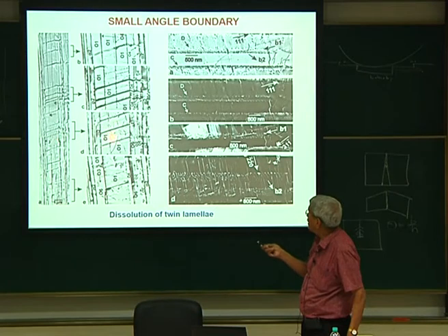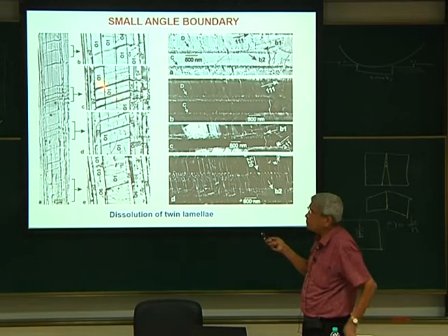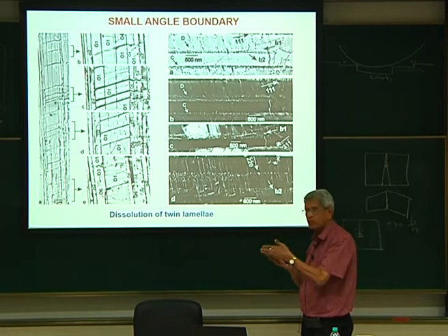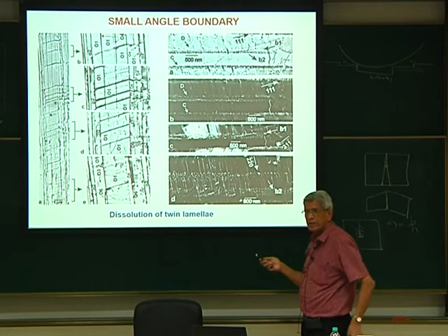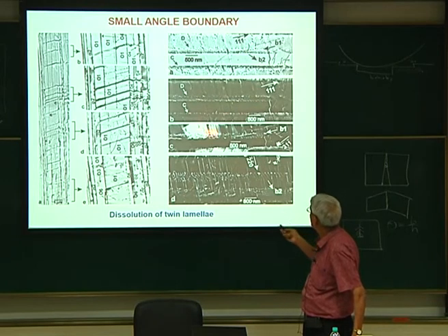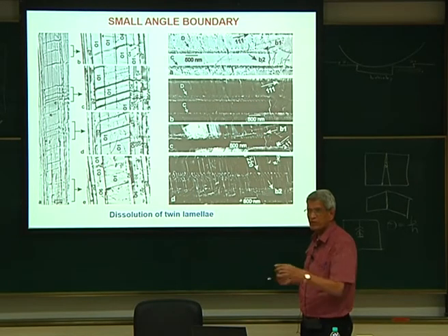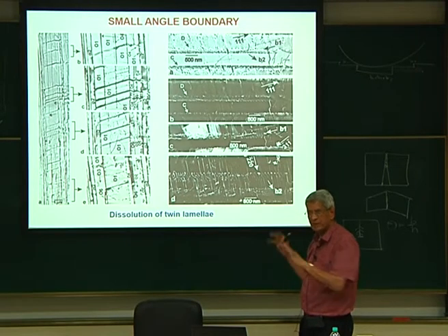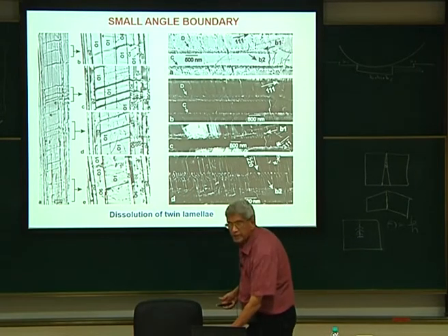Then, very far away from it, you do not see dislocations, and essentially the same boundary, where the twist boundary was parallel to the beam, is now tilted, and when it is tilted we can see two sets of dislocations. These have been analyzed. From this we can find out the network of dislocations, and from the spacing between the dislocations we can try to calculate the twist angle. That is essentially what has been done in this case.